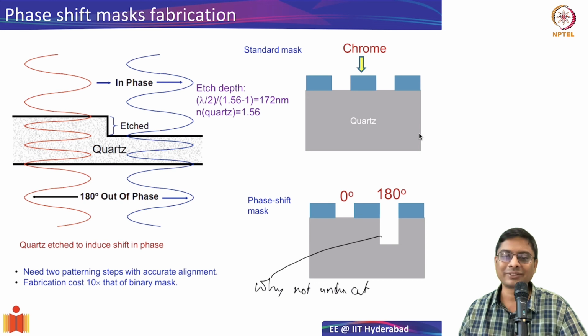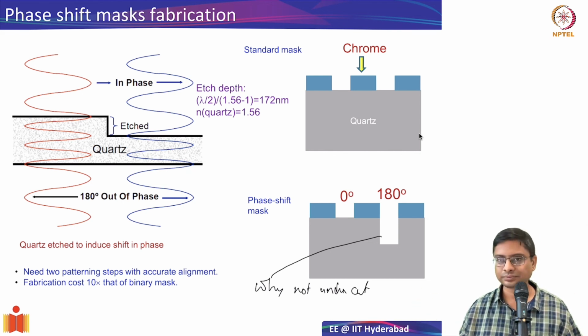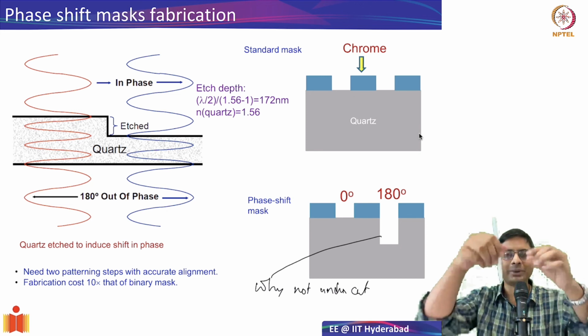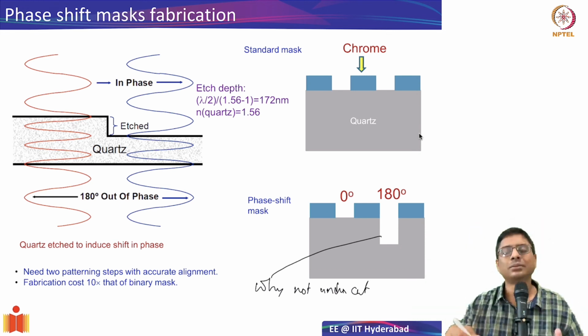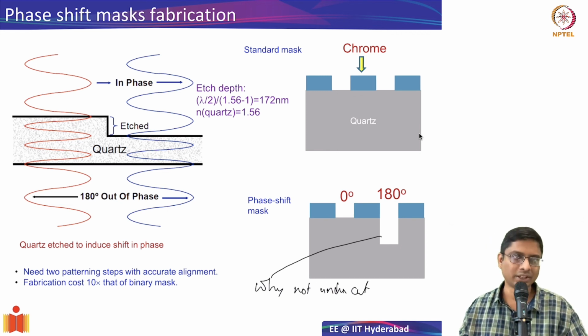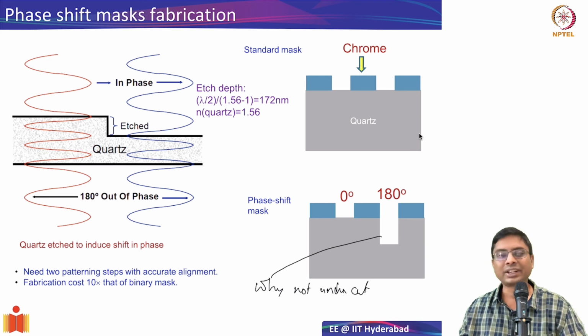So there are various etching tools. One, ferric chloride, we talked about, was called wet etching. You have a liquid which is going in. But in addition to that, we can employ what are known as dry etching techniques, which use gases. You have a gas under low pressure, and you make sure that the etchant atoms go only vertically. By doing some tricks with that, you can etch vertical structures like this with a minimal amount of undercut, or more anisotropy. All right. So this is about dry etching, and you can create a phase mask like this. So a lot of optical techniques can be applied.